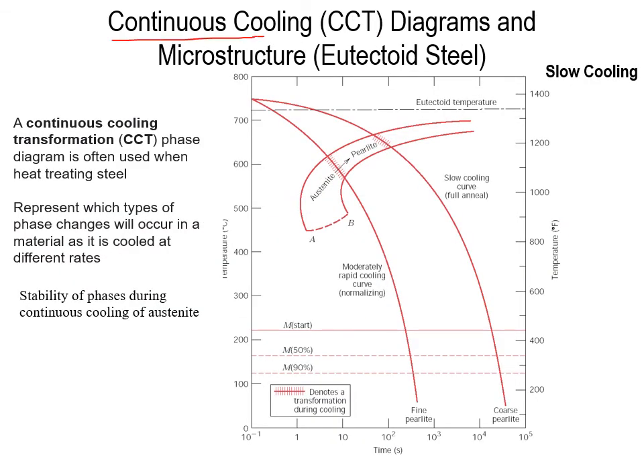Now we're going to take a look at the continuous cooling diagram and microstructure for eutectoid steel. A continuous cooling transformation, or CCT, phase diagram is often used when heat treating a steel. This represents which types of phase changes will occur in a material as it's cooled at different rates. So, stability of phase during continuous cooling. We can see here we have our austenite, and denoted down below is a transformation occurring during cooling by this symbol here. There's our transformation of austenite into pearlite, and then another transformation here. This goes into a coarse pearlite when it crosses that line.